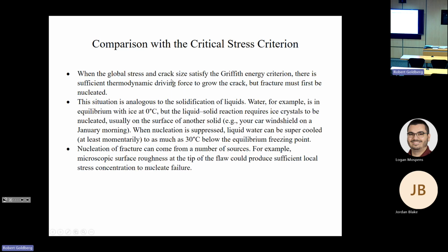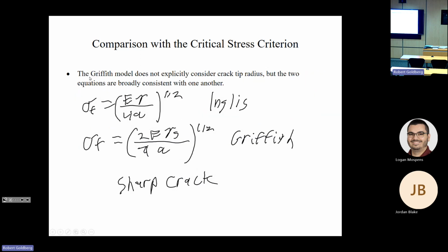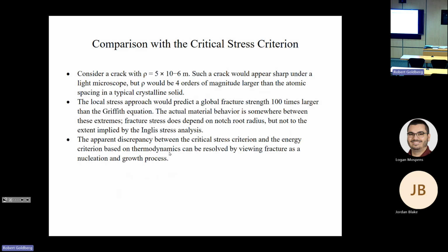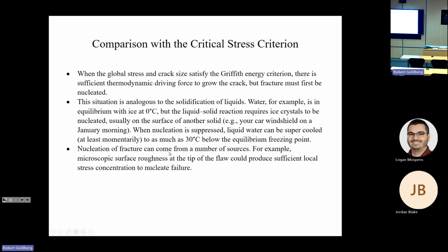What that means is when you have your applied stress and a crack size that satisfies the Griffith criteria, so you go to the Griffith equation, and you have your crack size, your applied stress, and your surface energy, everything looks like it would satisfy the Griffith criteria. There's a sufficient thermodynamic driving force to grow the crack, but first there must be something to trigger, nucleate, or kick off the fracture process. An example the book gave, which I kind of like, is analogous to the solidification of liquids. When you cool water to 32 degrees Fahrenheit, 0 degrees Celsius, water turns into ice. But normally, you have to nucleate or initiate this process.